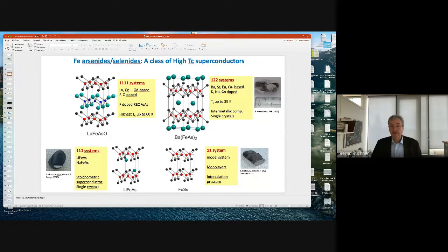Again, there's just a lithium in between there, or even the simplest one, iron selenium, where you have just iron selenium layers and nothing in between. Both of these are very famous as well. So you see, this is a van der Waals coupled system. This is a 2D system. And indeed, if you go down to the monolayer, which we are also now able to do, and others as well, there is evidence for high TC superconductivity if you go to the monolayer.